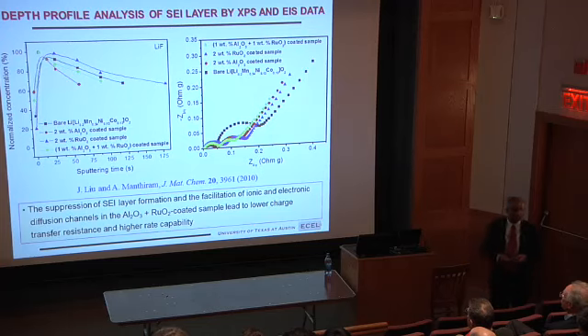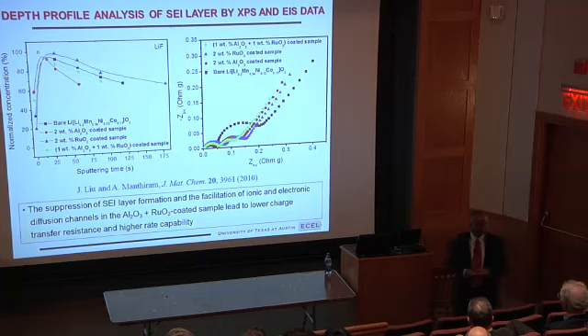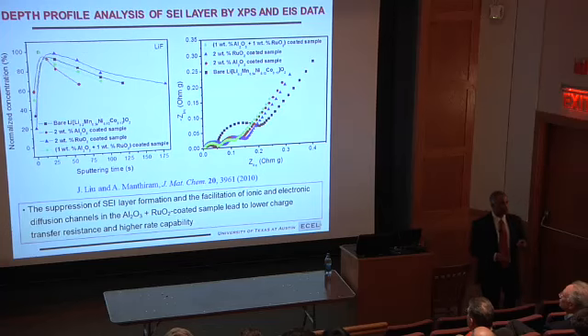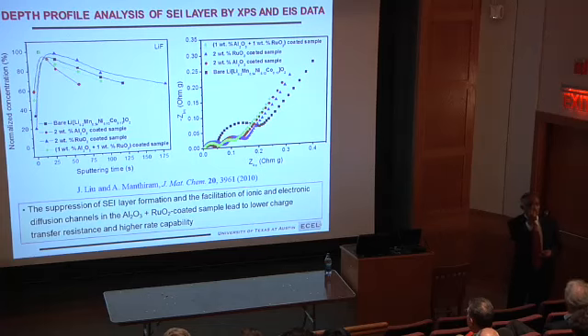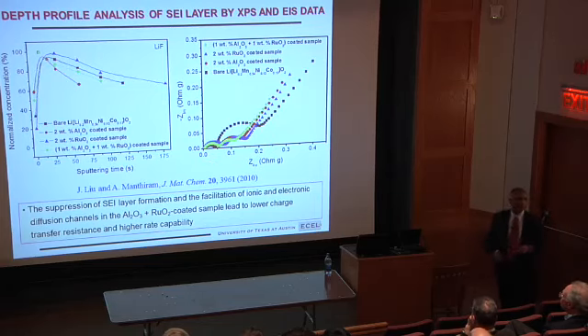Instead of aluminum phosphate or aluminum oxide, we put ruthenium oxide because that's a good metallic conductor, should help. But as you know, ruthenium oxide is a good catalyst. So it catalyzes the oxidation more. So that's worse than the bare material. So conditioning the surface helps to decrease the irreversible capacity loss. It also helps to increase the rate capability because you are suppressing the solid electrolyte interface layer formation, and that's reflected in the impedance. Less impedance the coated material has.